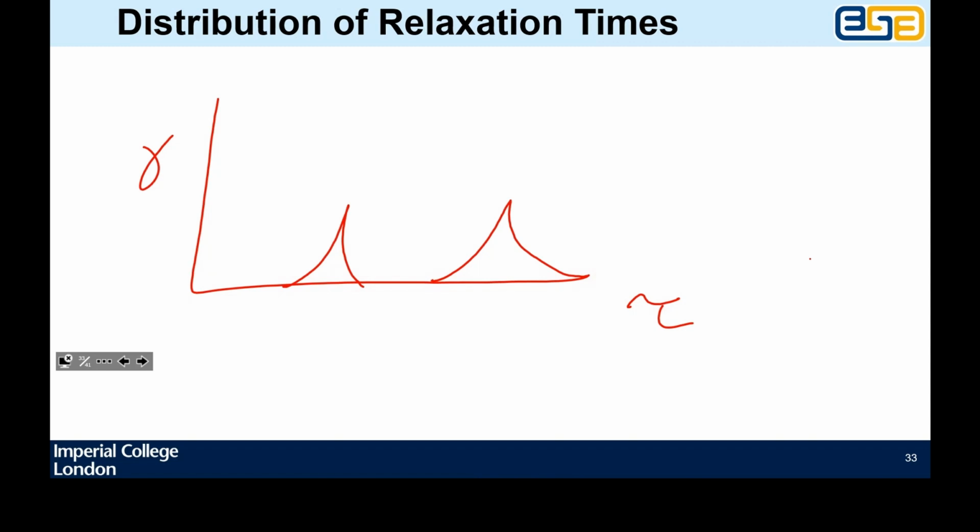However, it's never as simple as you might expect, and you have to add more data in order to make this transformation coherent, and you end up doing various kinds of regularization to fit nice curves to the data so you can have a greater degree of discretization, and that causes no end of problems. So if you see a beautiful DRT plot, your first thought should be suspicion, because a lot of processing had to be done to turn your impedance data into that DRT plot. They are wonderful when you have them, but the data had to be treated quite significantly to create it. So that's something to bear in mind.